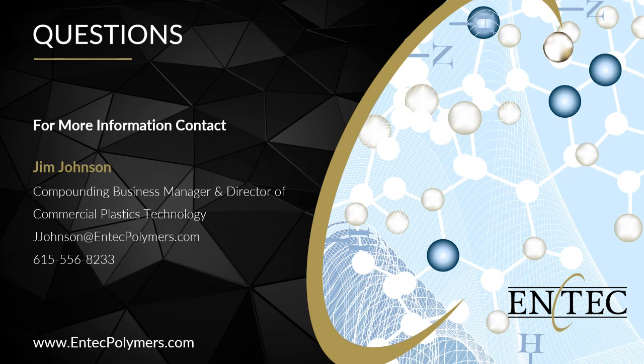I see a question here that says, what do you recommend as a compatibilizer for TPS and PLAs? Well, I assume for TPS, you mean thermoplastic starch, and PLAs. In many cases, there's a couple of options for the PLAs. The first one, because a PLA is a polyester type material, I would recommend a glycidyl methacrylate compatibilizer for that. You could also use butyl acrylates. That's one of those acrylate copolymers, so that's another option. You could use maleic anhydride grafted, again, but I would recommend that glycidyl methacrylate first for that application.